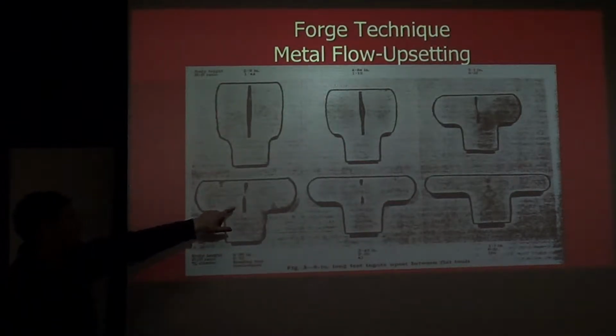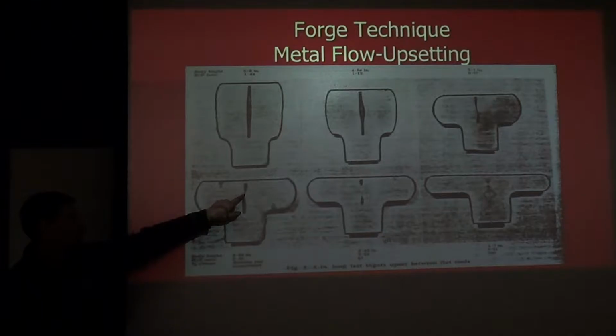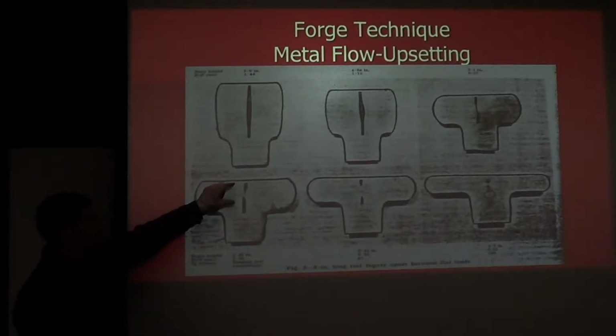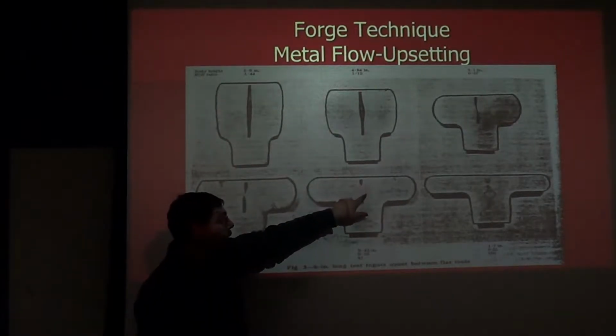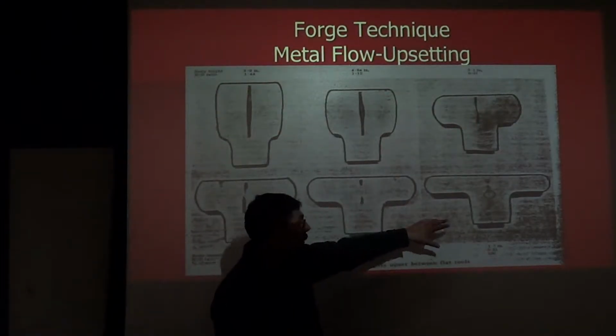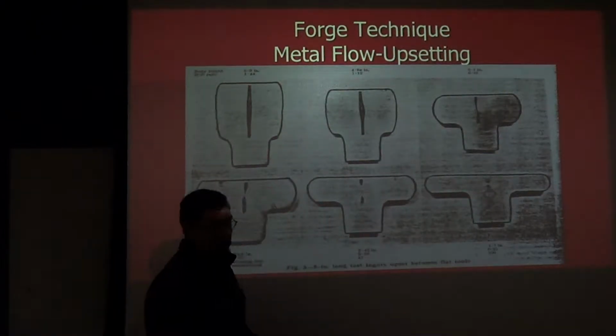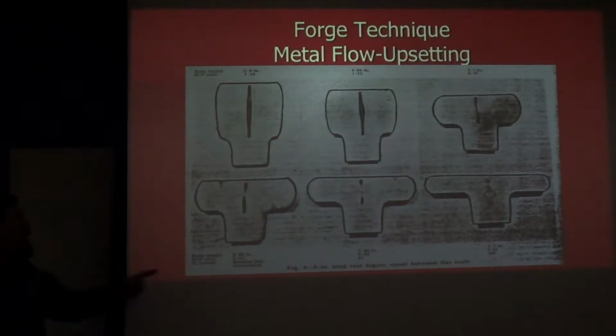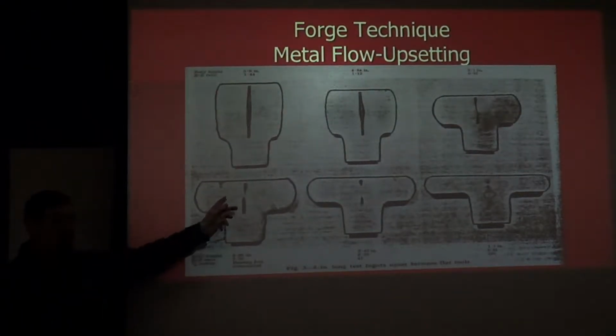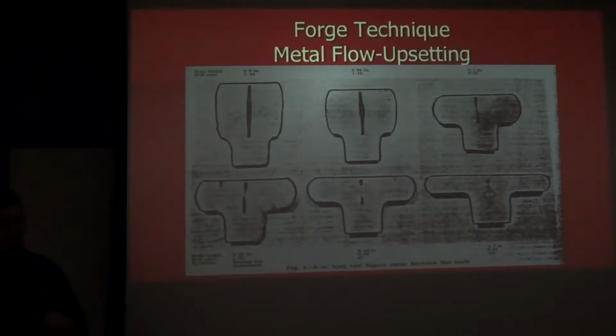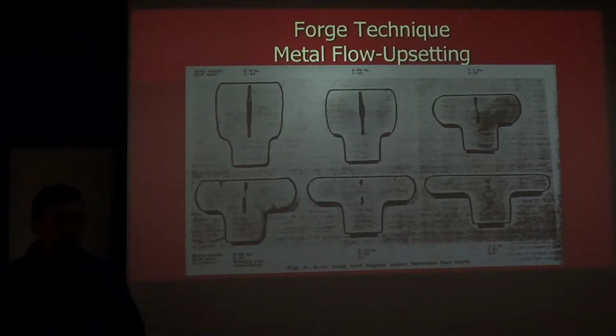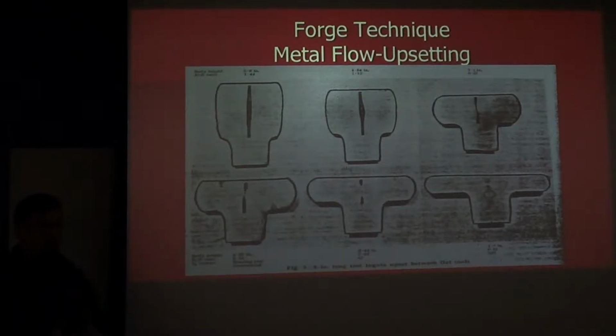Right here, though, we see that we've actually got some bonding happening. So this is the point at which those two friction pyramids, if you can imagine being there, are starting to intersect with one another. And we can continue the process and eliminate a bit more. Now, in this particular example, they were never able to completely eliminate the hole, but they got rid of most of it. This position here, where they first start to get the hole to go away, occurred when they had a 2-to-1 reduction in height or length. So they did, what we would say is, an upset of 2-to-1.